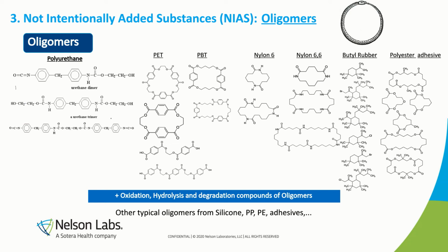Typically, during the polymerization, and this is mainly true for anionic or cationic or radical polymerization, you have some kind of site of the polymer where the propagation takes place. And when that site encounters the tail of the polymer, there's some kind of ring closure, and that stops the polymerization, of course, completely. So that's why you see a lot of cyclic compounds as oligomers.